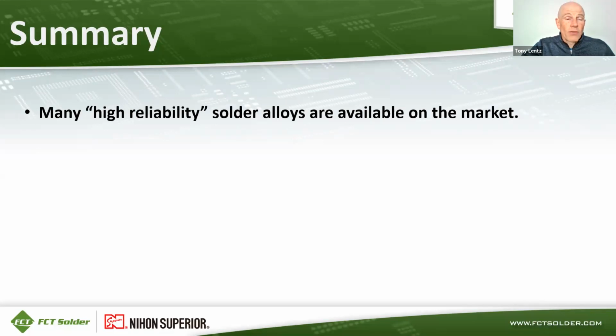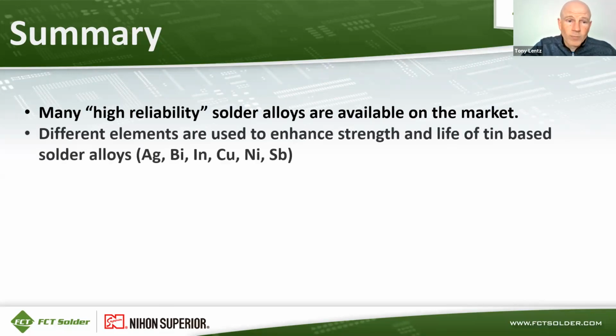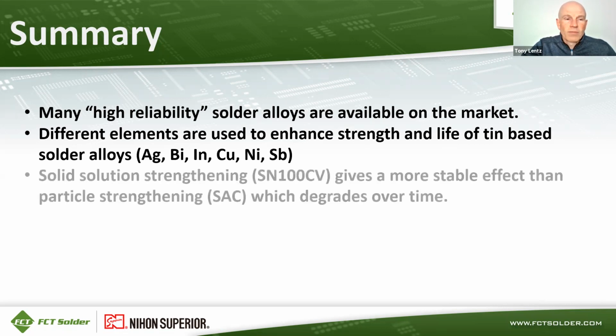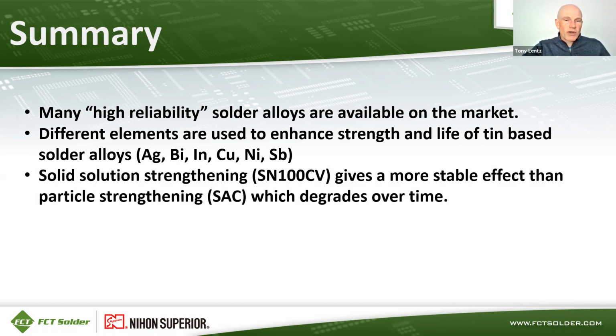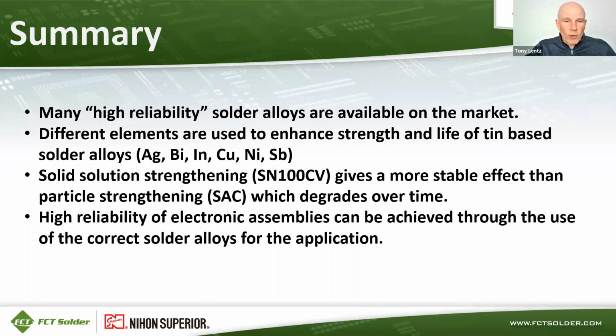So in summary, there are many high reliability solder alloys that are available. There are different elements that are used to enhance the strength and the life of these tin-based solders, including silver, bismuth, indium, copper, nickel, and antimony. And sometimes combinations of all of them are used. Solid solution strengthening that's used in SN100CV gives a more stable effect than particle strengthening in SAC type alloys, which degrades over time. But with all of these different solder alloys, we can achieve the creation of high reliability electronic assemblies. You just have to make sure you pick the correct alloy for the application and you understand what type of conditions it's going to be subjected to, to make an educated decision on the correct solder alloy.